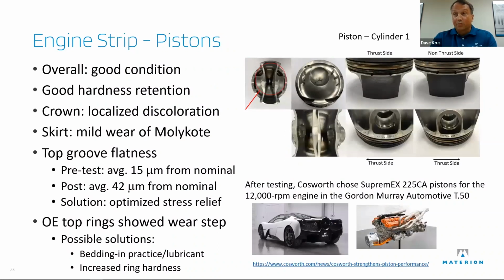To look at the pistons, actually, condition was fantastic. If you go to the white paper, you could see the hardness retention. It was really, really good over the time. Little discoloration on the crown, as I mentioned, and you can see it right here as well. That's one of the pistons from the test. A little bit of wear, that's the opposite side, the thrust side. You can see just a little bit of wear if I put it in the light the right way there, of the moly coat.